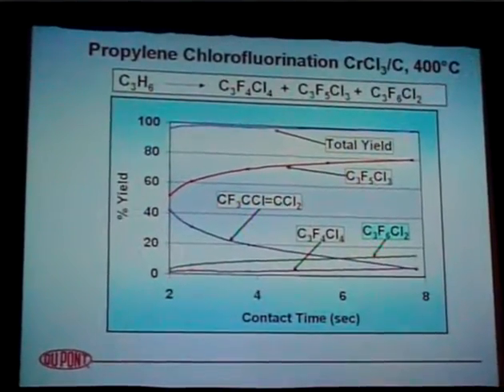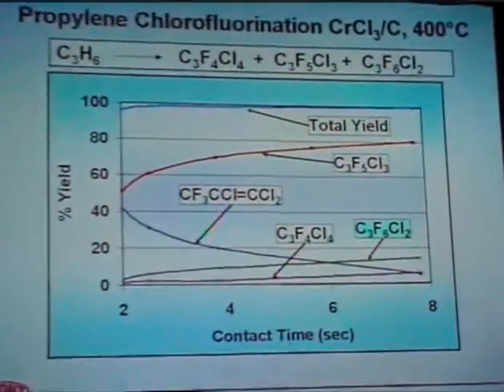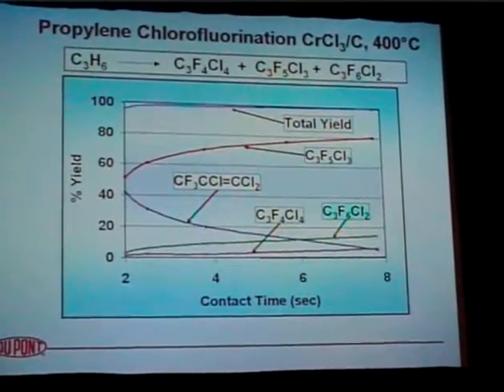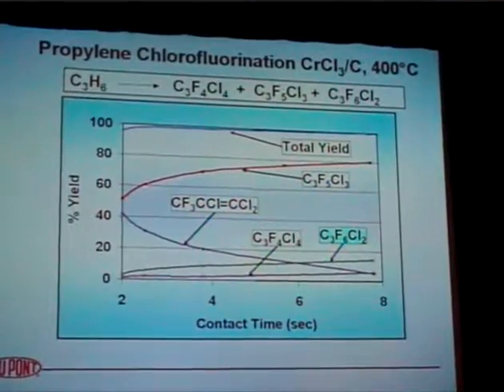This chart shows the product distribution as a function of contact time when you start with propylene and react with chlorine and HF over a chrome chloride and carbon catalyst. If you look at the top line, you can see that the total yield is very, very high. The first time you run this reaction, you see dozens of peaks in the gas chromatograph, and you say, whoa, we've got a long ways to go here.